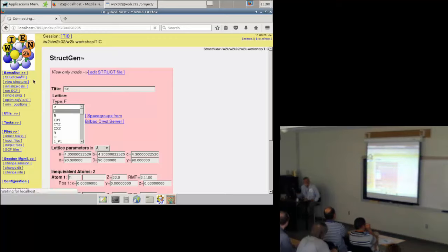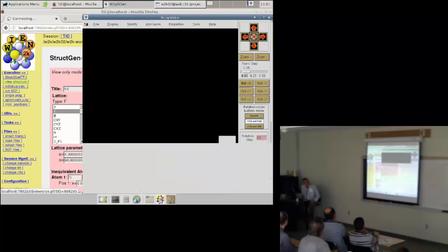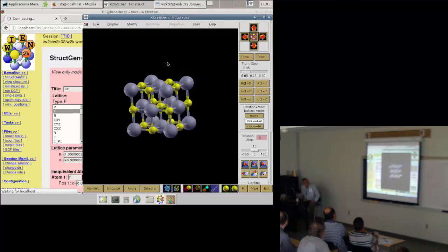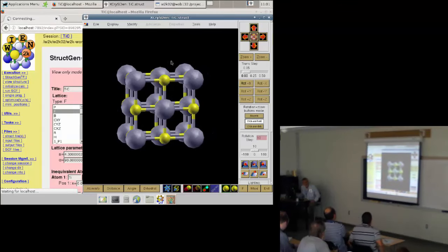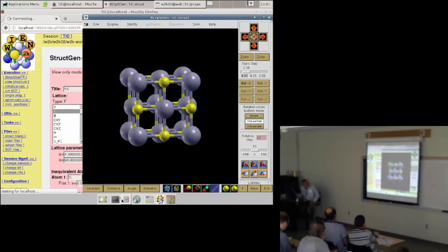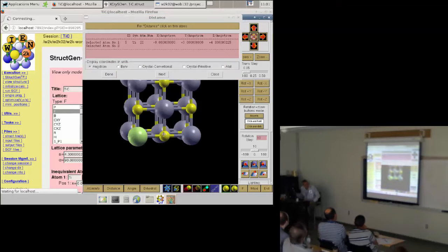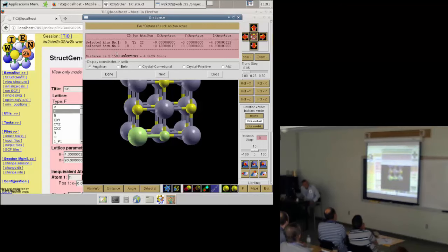Whenever you have finished the structural input, please verify it is correct — look at the structure. We use the external program XCrySDen, and you can nicely see a sodium chloride structure. In more complicated cases I really recommend that you click on 'distances', click on two atoms, look at the distance, and check that it agrees with what is in a paper — this ensures you didn't mistype an atomic position or a lattice parameter.